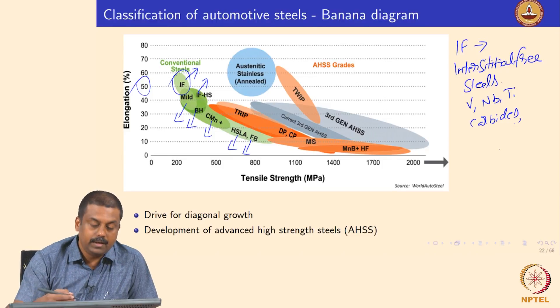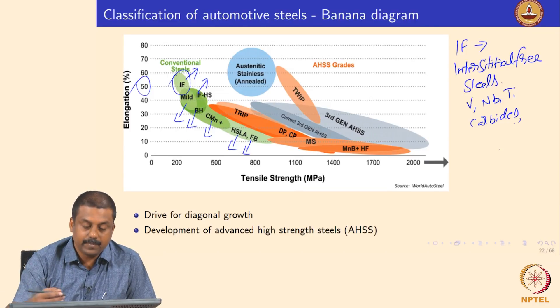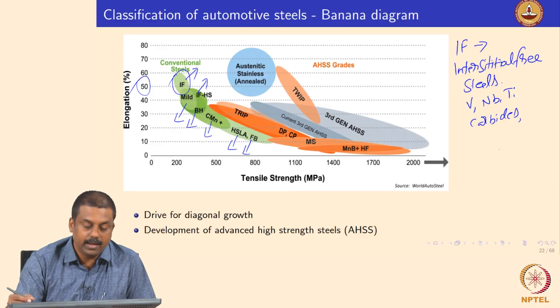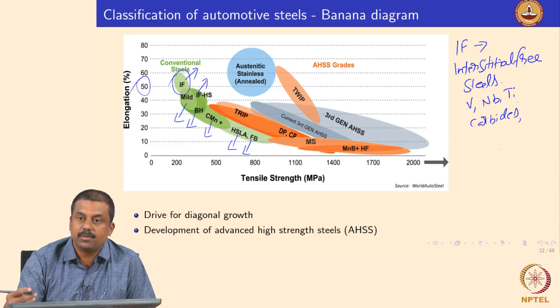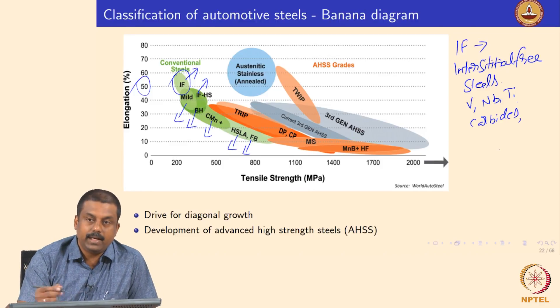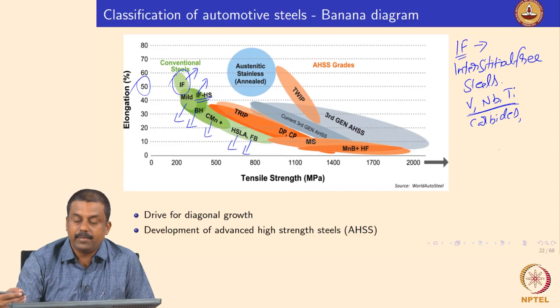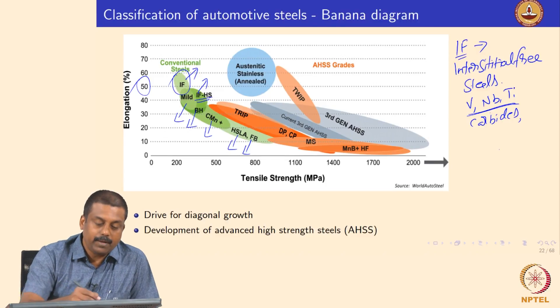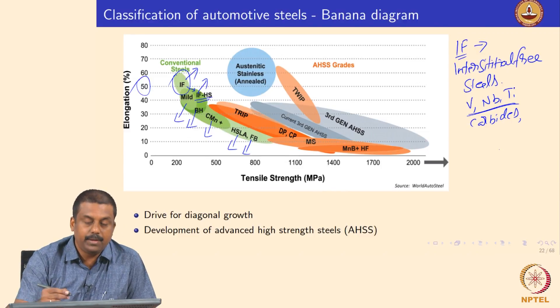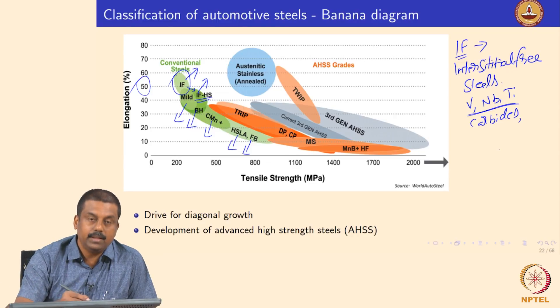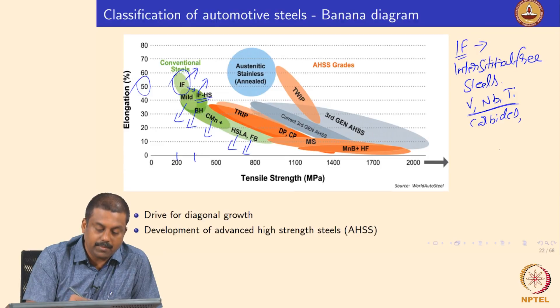The trend moved toward identifying high strength steels. Automakers wanted to increase the strength of the steel, so they started using somewhat higher amounts of alloying elements such as vanadium, niobium, and titanium to form more carbides, thereby increasing the strength slightly higher than conventional IF steels. The IF high strength steel — interstitial free high strength steel — possesses a slightly higher amount of micro-alloying elements of niobium, vanadium, and titanium, increasing the precipitate volume fraction to provide precipitation hardening. The strength increased from about 200 to about 300 MPa.